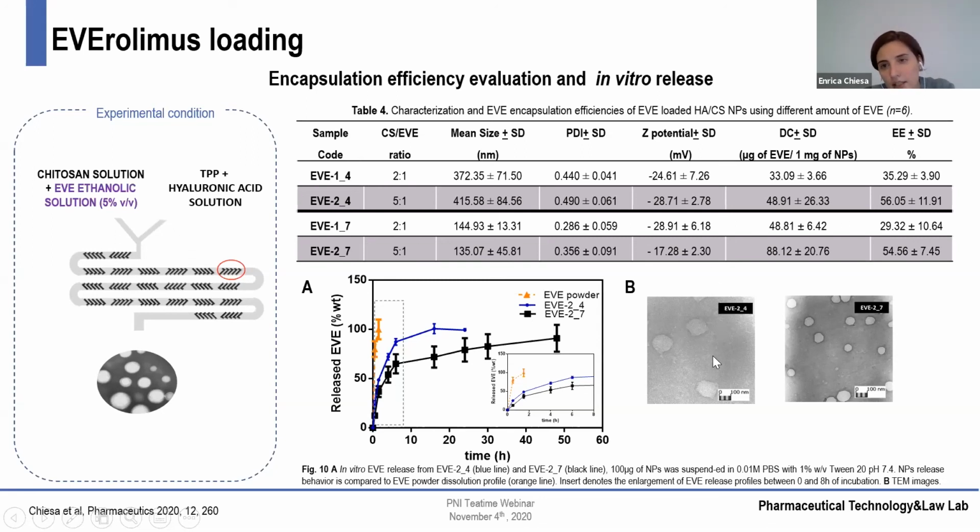TEM images confirm the spherical shape of the nanoparticle, and on batch 2.4 and 2.7, in vitro release test was performed. And as you can see here, both formulations are able to prolong the drug release till 16 and 48 hours, compared to the drug dissolution that is completed in 2 hours.